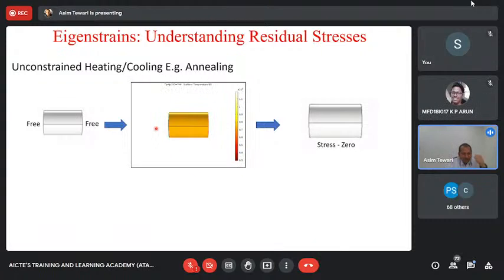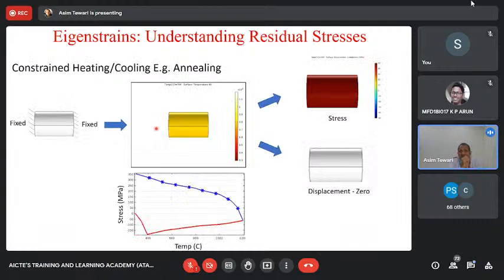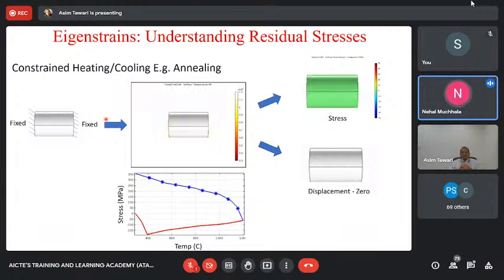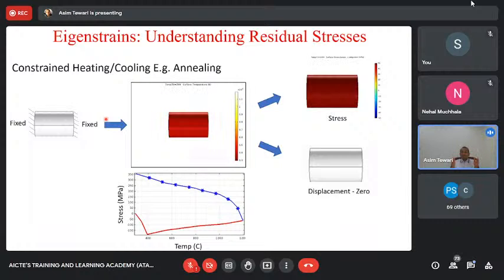All right. Now I will change the thing. Now I will have a part which is not allowed to expand. So if you see, it's no more free. It is fixed from both the sides. So I have a cylinder which is fixed from both the sides now. Since it is fixed from both the sides and I'm heating it up, what would you expect? Do you expect it to expand? No, there will be restrictions. So expansion will not be permitted. And because of that, stress will be developed. Absolutely. You will not allow expansion to happen, and because expansion will not happen, it will lead to stresses.